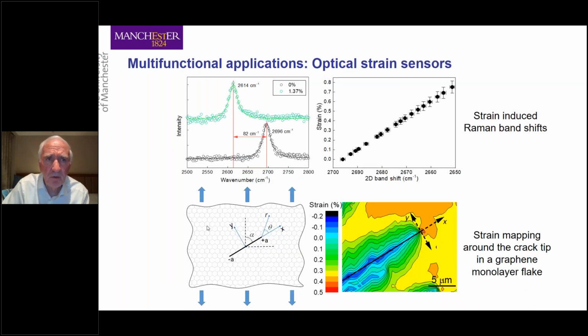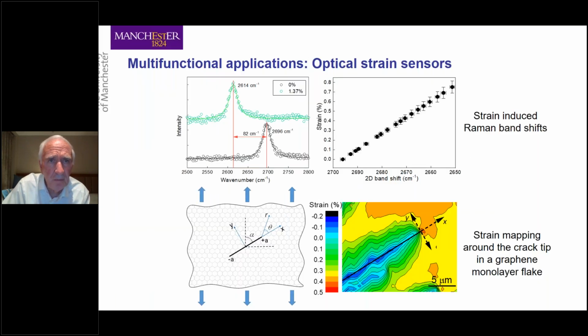So let's show you a particular example for a single flake of graphene, although you can probably extrapolate this up to a sort of structure which we saw in the first presentation, where you've got lots of graphene flakes. Again, this is essentially a single flake of graphene under stress in the vertical direction, and you can see that the Raman band shifts enormously when you deform the material over 1% strain. And if you measure the peak position of the Raman band against strain, you have this linear relationship. So once you know the peak position, you can read off the local strain.